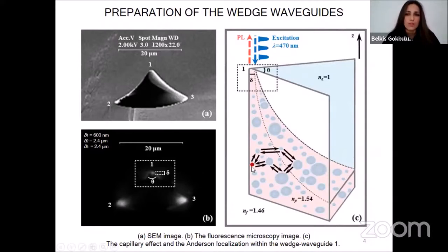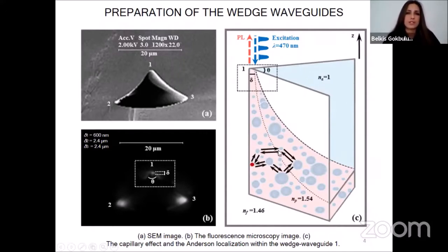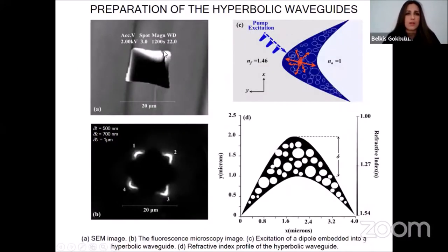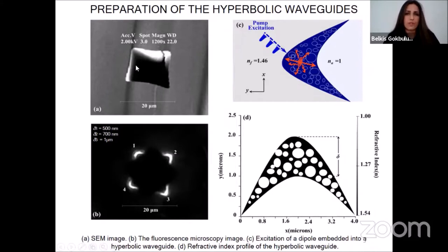When the localization length is comparable with the wavelength of light, the scattered light waves return to the same spot to constitute a loop, trapping photons at particular frequencies and generating Anderson localized modes. The hyperbolic optical waveguides are also produced inside a 3D micro-capillary delta-shaped cross-sectional area using the same capillary process at the same conditions. The SEM and fluorescence microscopic images of the hyperbolic optical waveguides are demonstrated in figures A and B respectively. Each waveguide shown as a bright spot ensures a number of coupled optical modes based on the geometry and thickness of the waveguide itself.